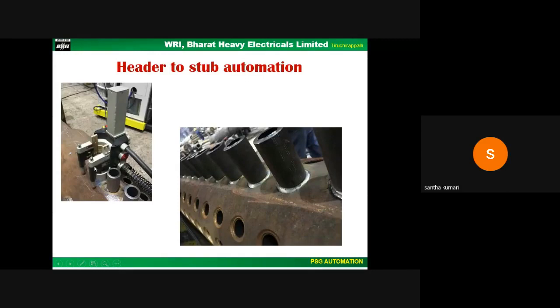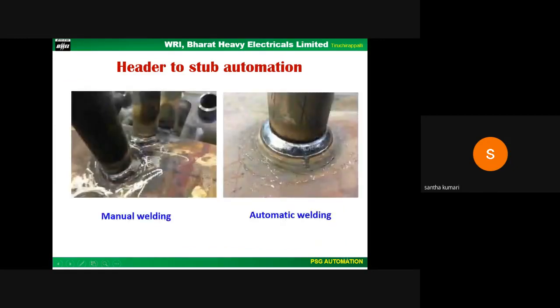Considering the pitch of the two adjacent stubs, this fixture development had to be considered. This kind of weld is carried out by the manual SMAW process, as I said earlier, with different sizes of electrodes. For the root pass a 2.5 mm electrode, then for further passes higher 3.15 or 4 mm electrodes had been used. The number of starts and stops, the slag removal, and the dye penetrant test in each layer were the limitations in manual SMAW, which could be eliminated by this kind of system. You can see manual welding as well as automated welding. We were able to get a full penetration weld here with this system. A demonstration had been done by the system manufacturer.